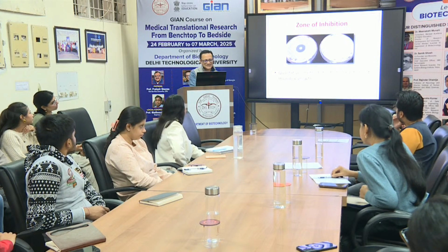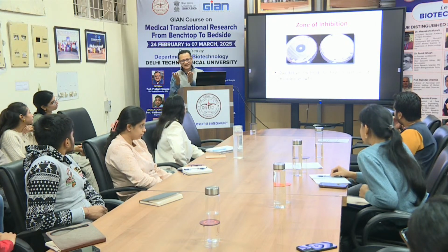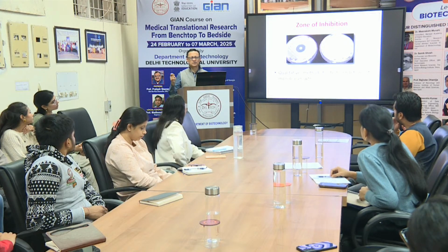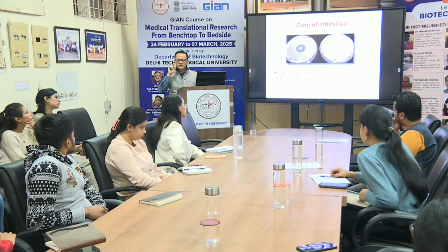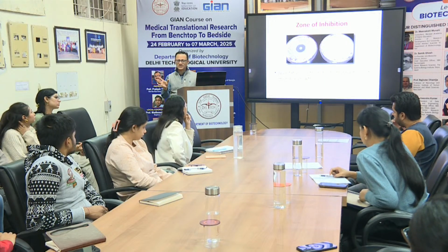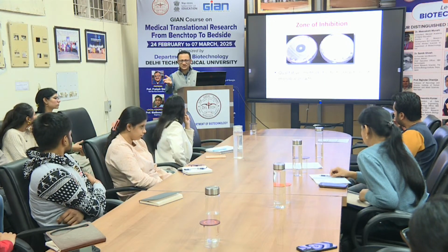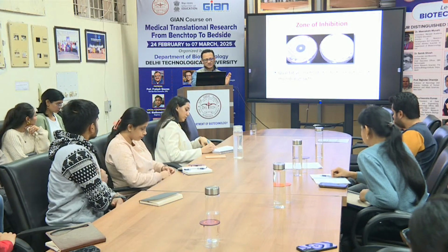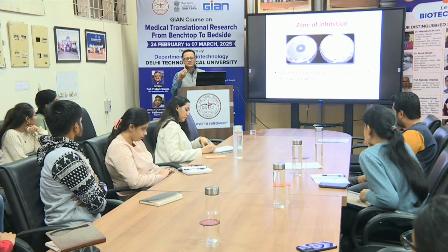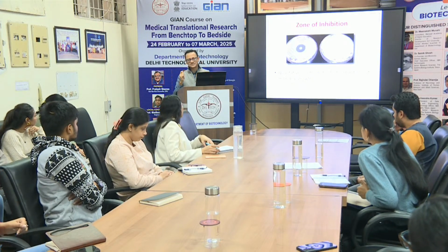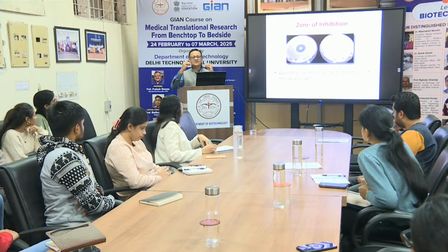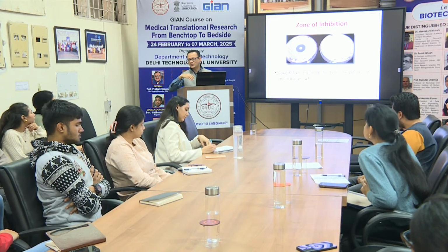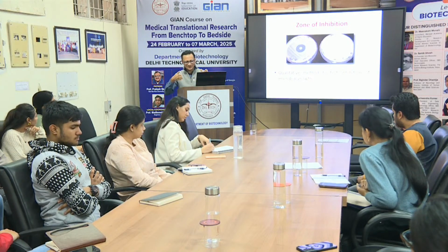Let's go back to doing a simple test, what sometimes people do. So let's say I'm saying my material is antimicrobial for 1 month. The easy method we can do, not that accurate but still okay, is you do a 24-hour bacteria study like we talked about, but your other catheter pieces, you put them in 37 degrees Celsius, pH 7.4 for 1 month.